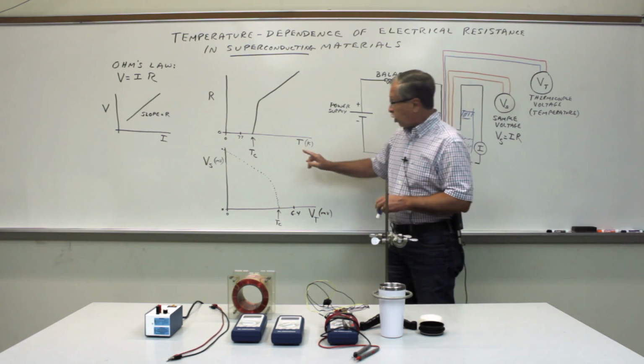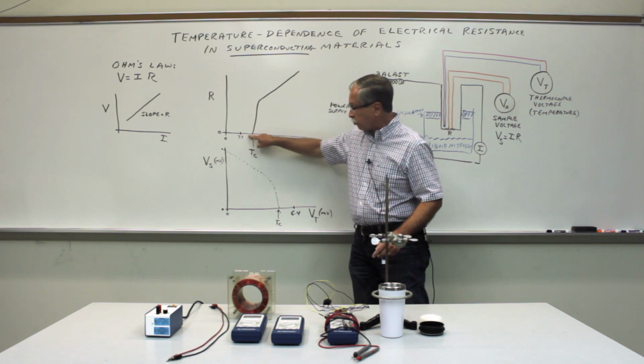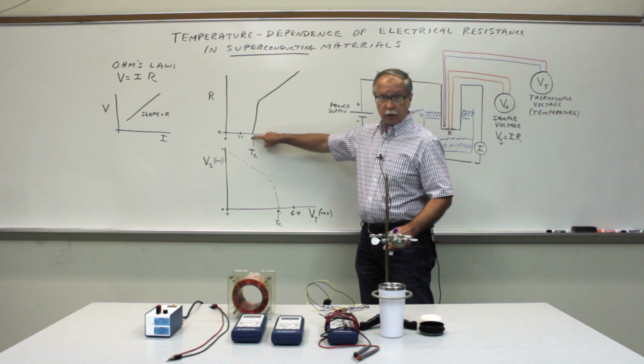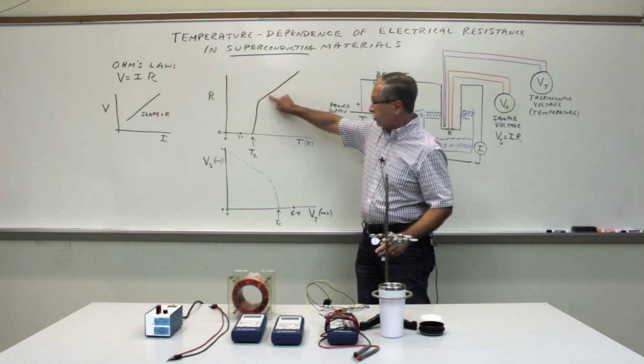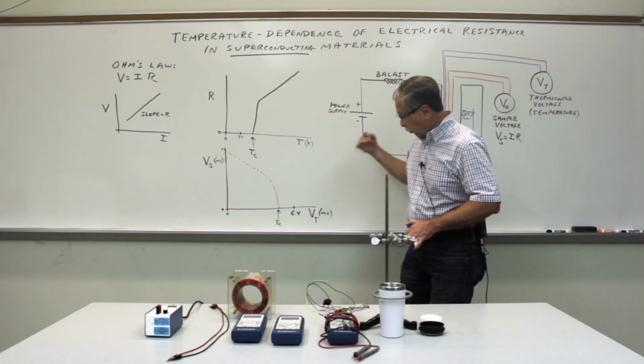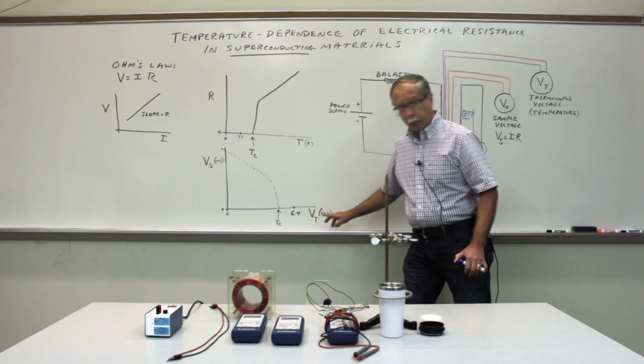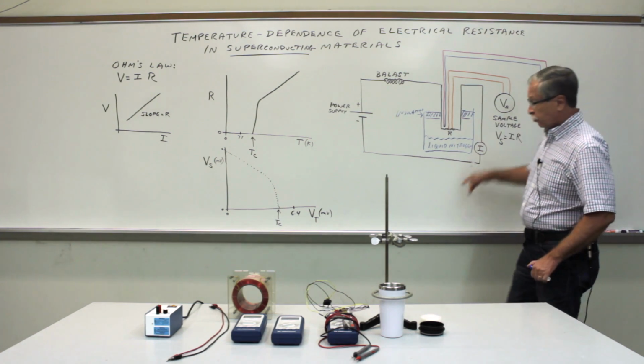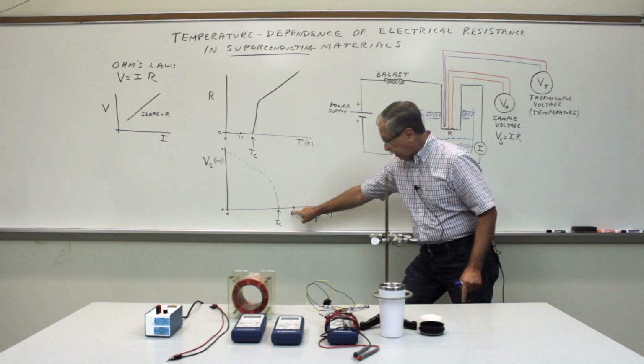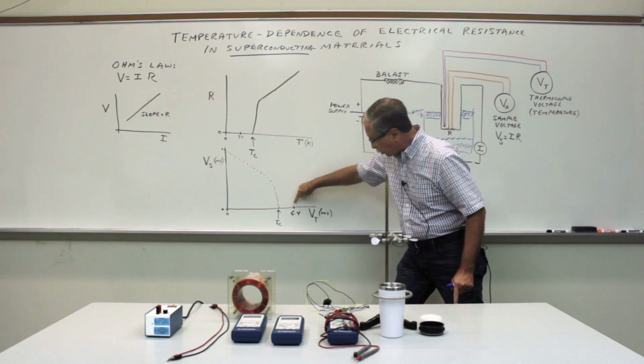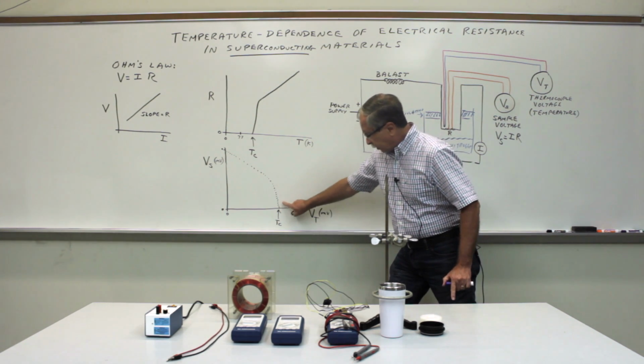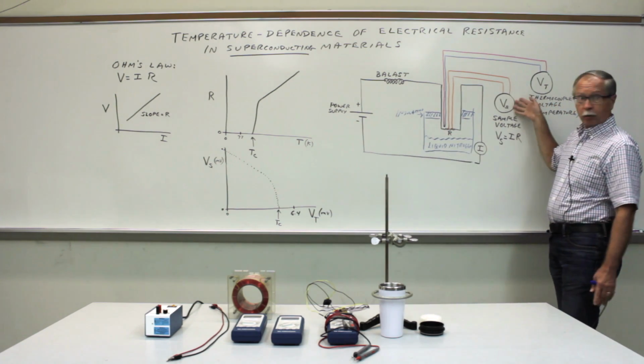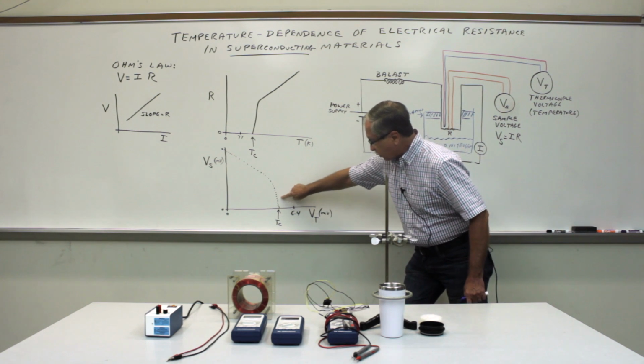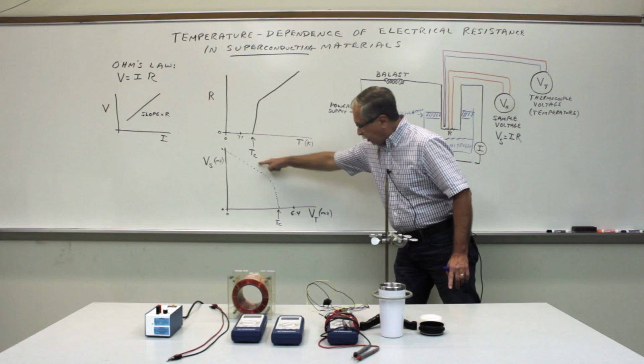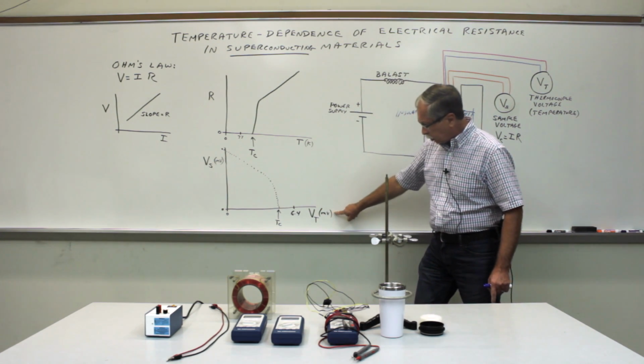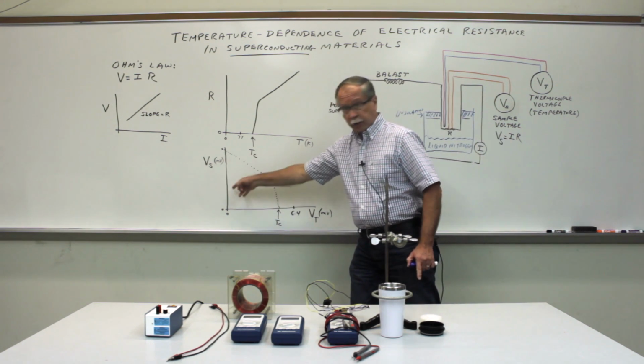So as the sample gradually warms up, it starts out at zero resistance in the liquid nitrogen, and then gradually warms up to the point where it ceases to be a superconductor, and the resistance reappears, and then it goes back to ordinary conducting. What you'll measure with your voltmeters is, again, 6.4 millivolts on the thermocouple voltmeter when the material is in the liquid nitrogen, and then when you raise it up out of the liquid nitrogen, it will gradually increase in temperature, and the voltage on the thermocouple will slowly decrease until you hit the critical temperature. Then the resistance on the sample begins to reappear, so the sample voltmeter will start to read something that's non-zero, and that will increase as the material warms up, and then it will gradually go back into ordinary conducting. So we'll use the thermocouple voltmeter to sense the temperature and the sample voltmeter to infer the resistance.